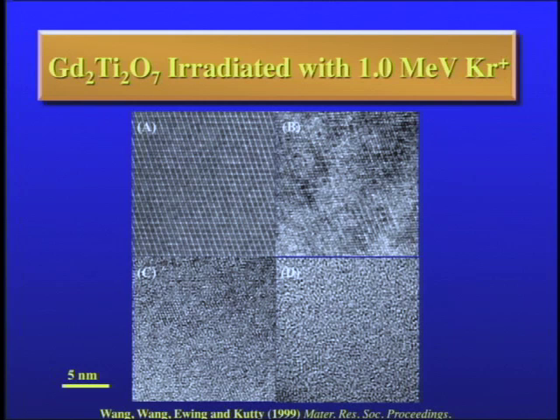And with high-resolution electron microscopy, we can see the change from fully ordered material, partially damaged, increasingly damaged with just islands of crystallinity, and then finally it's completely amorphous. Okay? So we get a lot of information, a lot of very detailed information about the damage accumulation process.